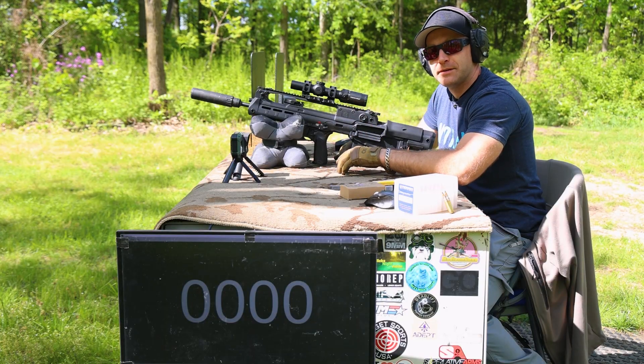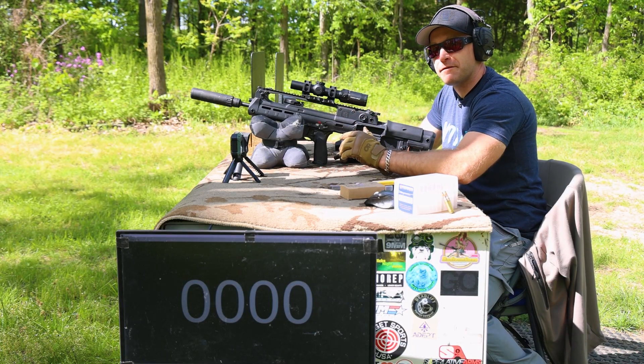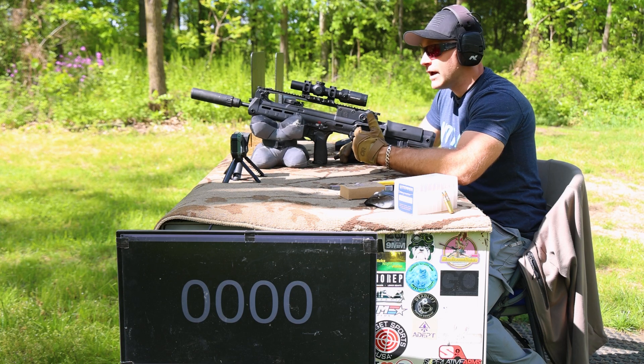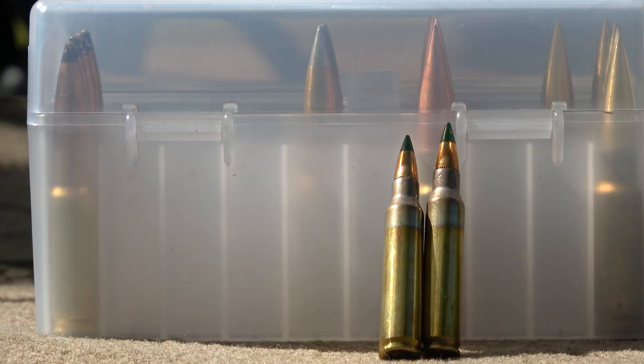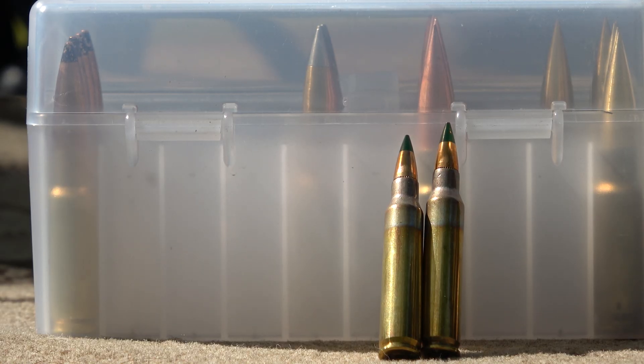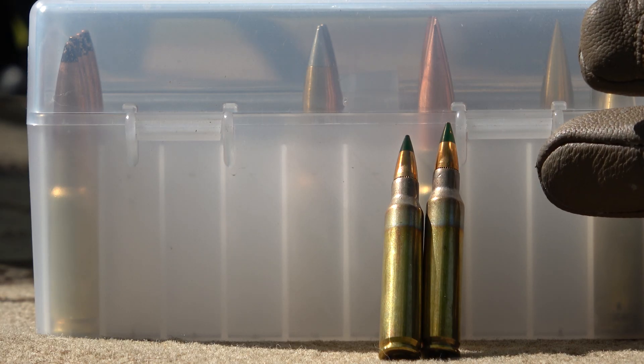Sample one, plate one is strapped in and ready to go. Per the workflow, we're going to start off with M855 from a 16-inch barrel and go up. Typically with polyethylene plates, they will struggle with M855 past a 10.5-inch barrel because it has a conical steel penetrating tip, right around 49-50 HRC, with a lead core.